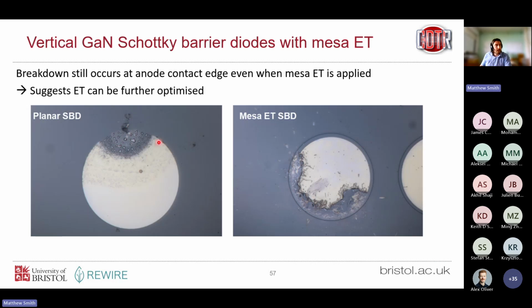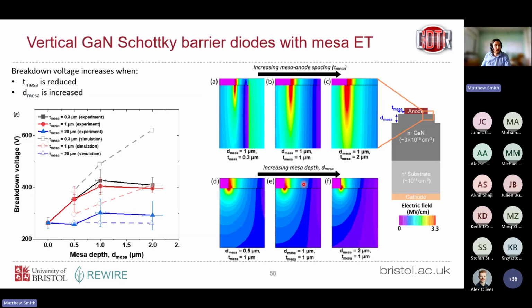So we do find that the devices do still break down at the edge. So this is without any edge termination. This is with good high breakdown voltage MESA edge termination. So we can still see the devices exploding around the edge of the devices here. So it suggests that we can optimize it further. We still do have a peak in the electric field at the edge, but our breakdown voltages clearly show an improvement. And again, simulation shows why that is.